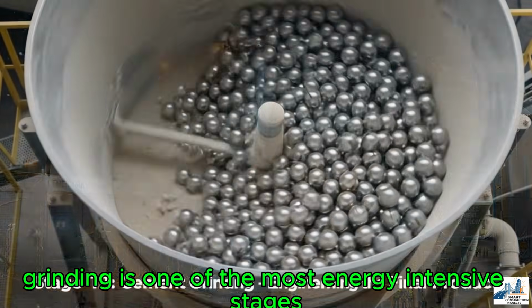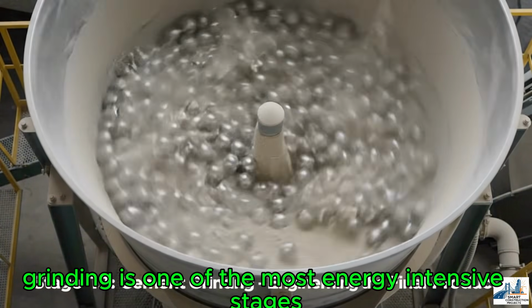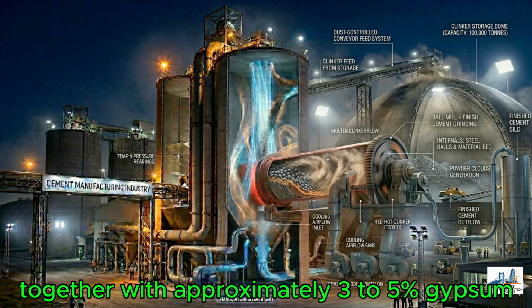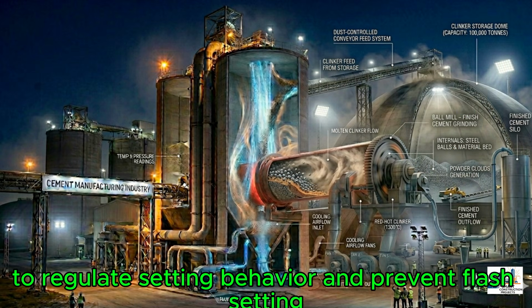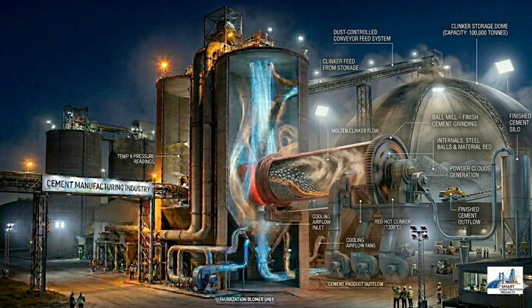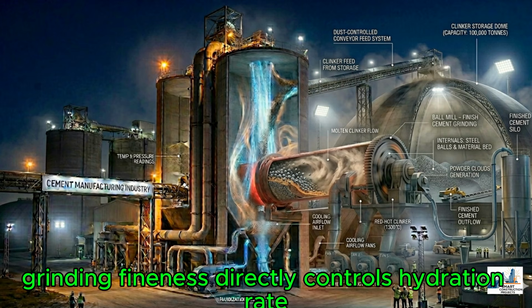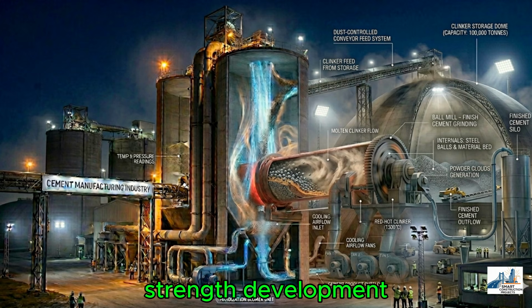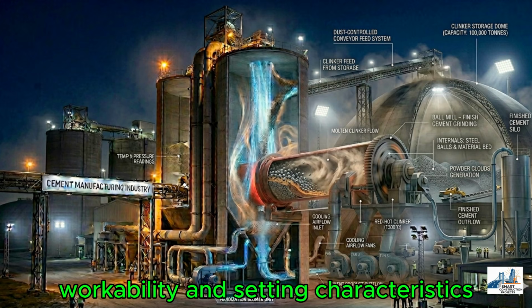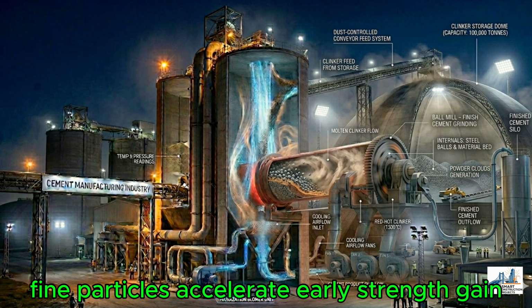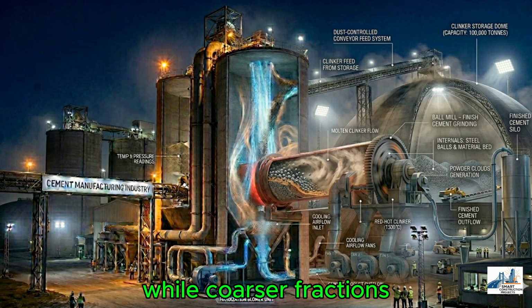Cement grinding is one of the most energy-intensive stages in cement manufacturing. Clinker is finely ground together with approximately 3 to 5% gypsum to regulate setting behavior and prevent flash setting during hydration. Grinding fineness directly controls hydration rate, strength development, workability, and setting characteristics. Fine particles accelerate early strength gain, while coarser fractions contribute to long-term performance.